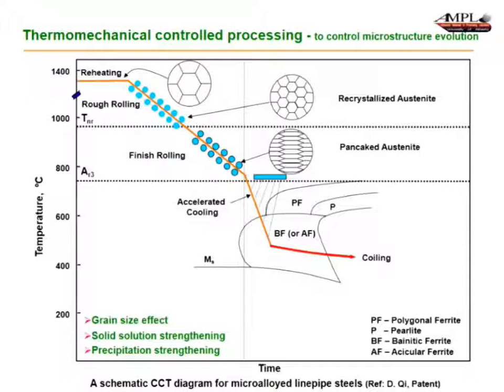So to study that, I'll get to that in a moment, but this is sort of the schematic of the portion of the process that we're going to really initially address. This is after casting. The steel goes through reheating. It goes through some rough rolling and finish rolling, forming the pancake austenite, and then finally accelerated cooling. And this is sort of superimposed over a CCT diagram where you try to control this cooling rate to get you into the right regime of the CCT diagram. And I'll say more about this a little bit later in the talk.